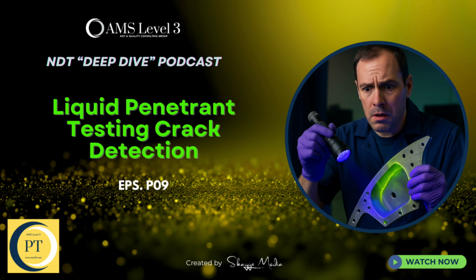It's more economical, uses less penetrant, but it also improves performance. As the part sits and drains, the lighter, more volatile solvents in the penetrant start to evaporate off the surface. This actually increases the concentration of the dye in the penetrant that is trapped down in the flaw. So it makes the eventual indication potentially brighter, more intense. Exactly. You get a stronger signal when it bleeds back out later.